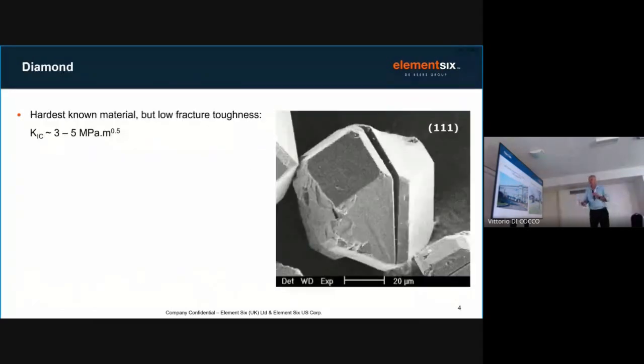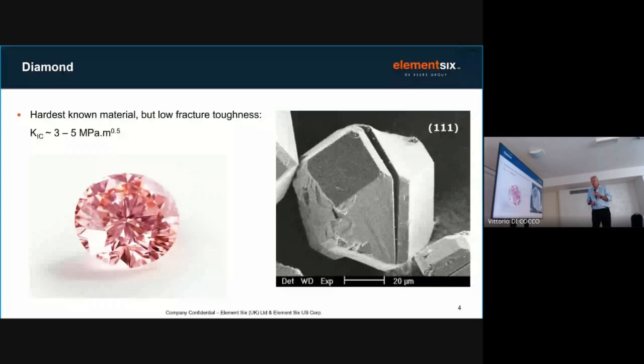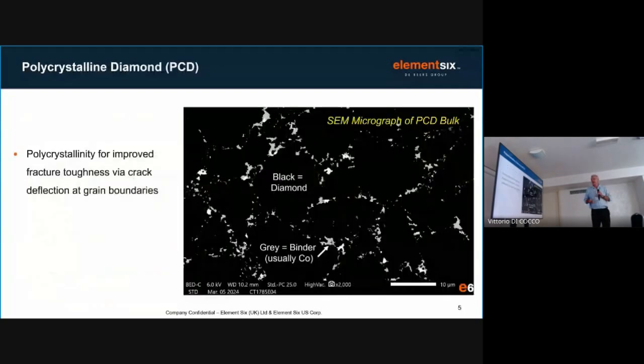So diamond, as you know, the hardest known material, etc., but very brittle due to the cleavage planes, of course. And there's a lovely version of a 111 cleavage plane, giving us a very low fracture toughness. So this is no good for an abrasive tool. Of course, it allows us to make wonderful gems and things, but not good for a tool. So we have to go polycrystalline.